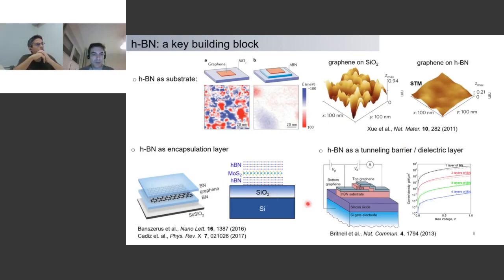But in addition to that, HBN has been used as an encapsulation layer for other materials like molybdenum disulfide or molybdenum diselenide. These 2D semiconductors react quite quickly under air exposure, so you want to protect them from the environment. One of the things you can do is encapsulate these materials with HBN. It protects them from the environment, but also improves, for instance, the optical properties significantly. There is some work showing that.